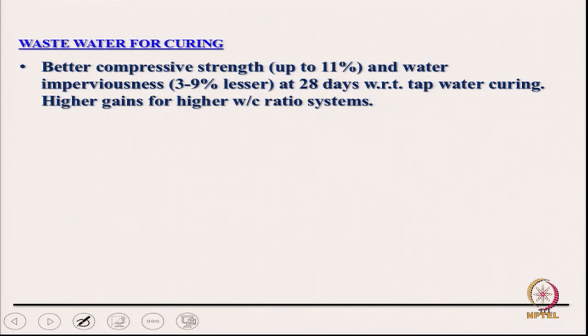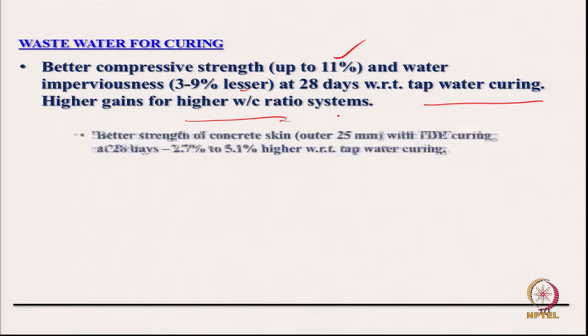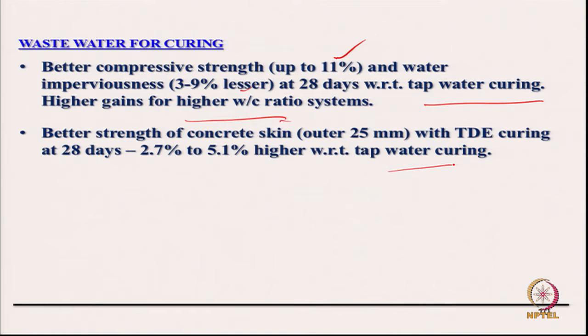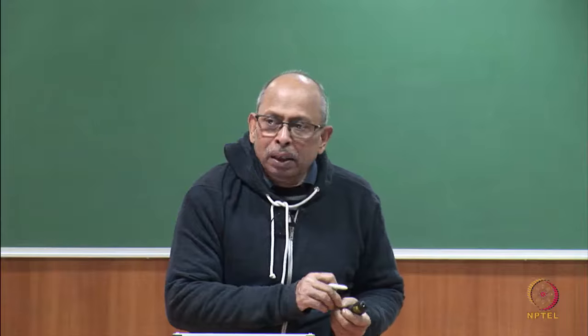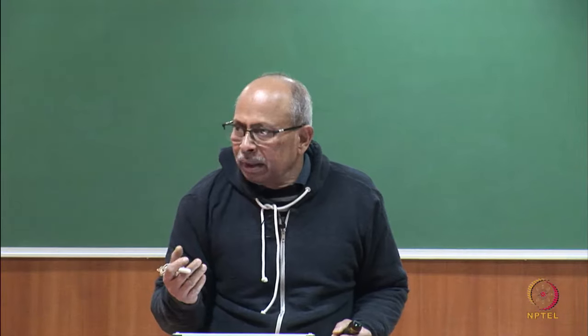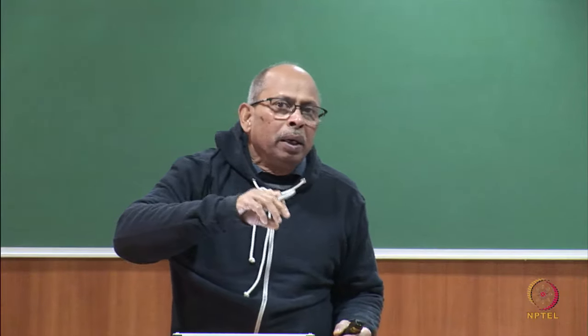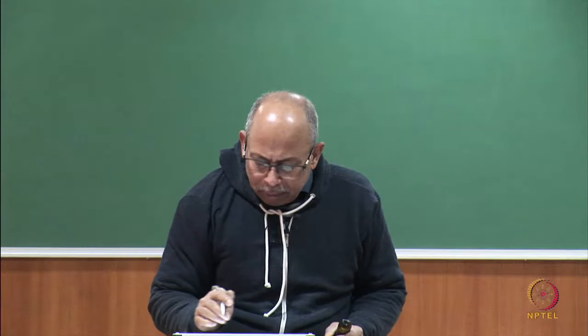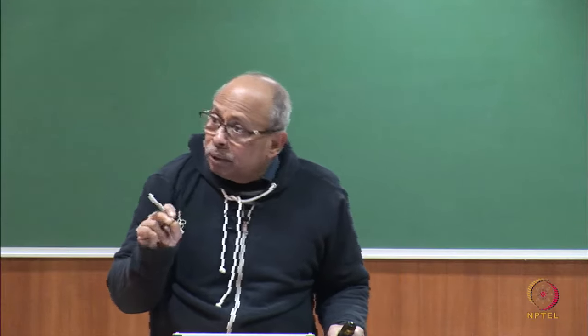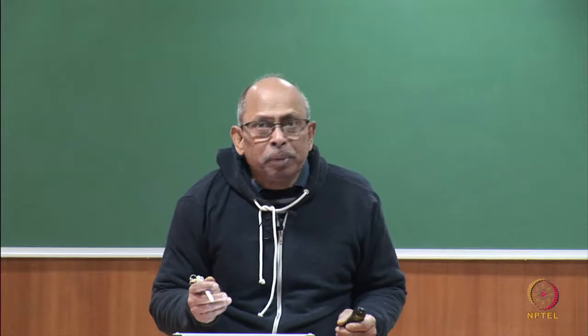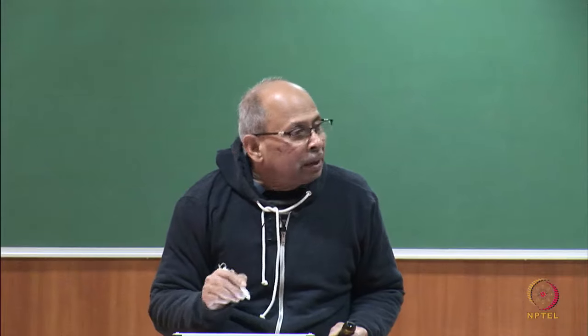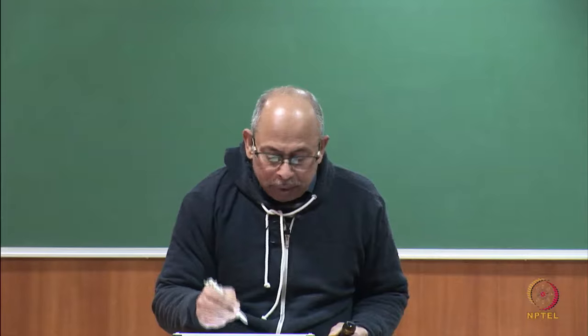Once they satisfy this, you can sometimes get better compressive strength, and water imperviousness also at the surface, with respect to some local tap water curing. So, higher strength gain, somewhat even higher, better strength for the concrete skin. If one tests through various kinds of testing, it is possible to test only the skin performance through something like surface hardness tests, or what is called a Capo test at the surface, a cut and pull out test. There are various tests available. You can find out the property of surface concrete, while your standard specimen is the cube specimen. Cube strength must be similar, but surface concrete is what is important from durability.